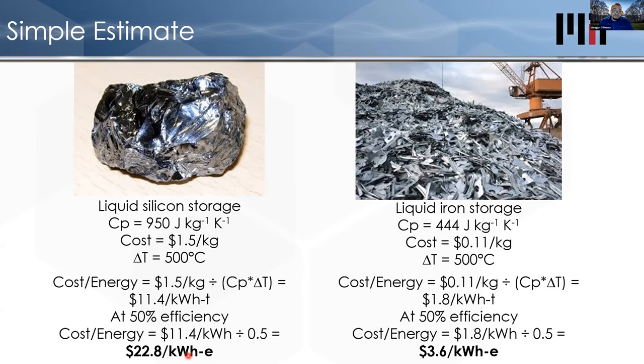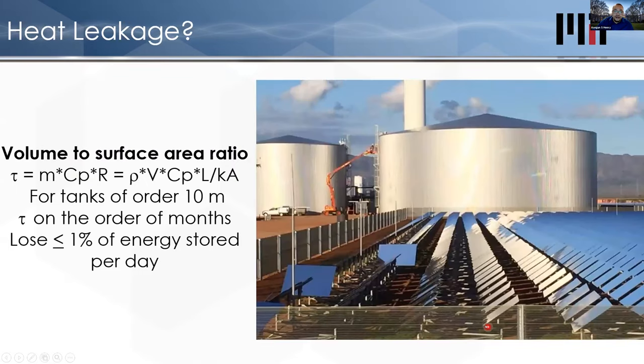Compare that with lithium ion batteries, which are slated to maybe get to $150 a kilowatt hour electric. Pump hydro is at $75 a kilowatt hour electric. So this is very, very cheap energy storage, quite a bit lower than the cost of lithium ion or other options. If you go to another material like liquid iron, if you take scrap steel, you can get even cheaper than that. You can get down to $3. So you can store energy insanely cheaply if you store it thermally. And so this is the direction we've been looking at going.